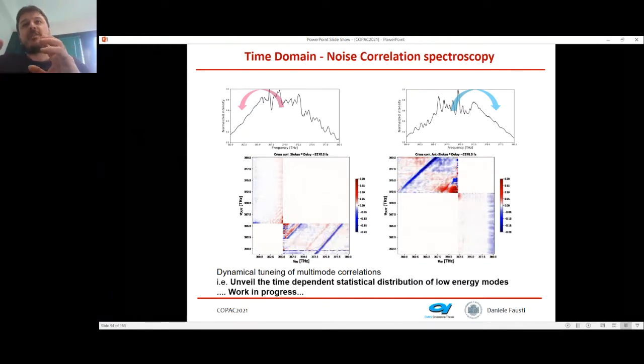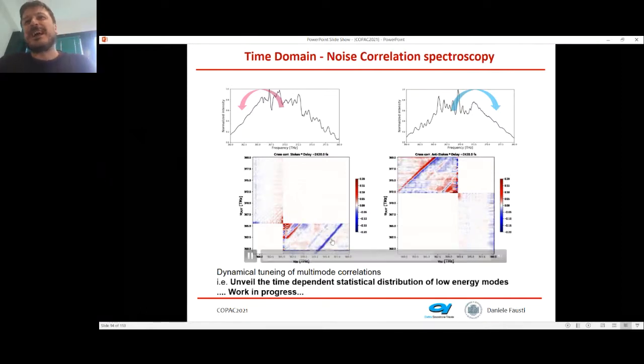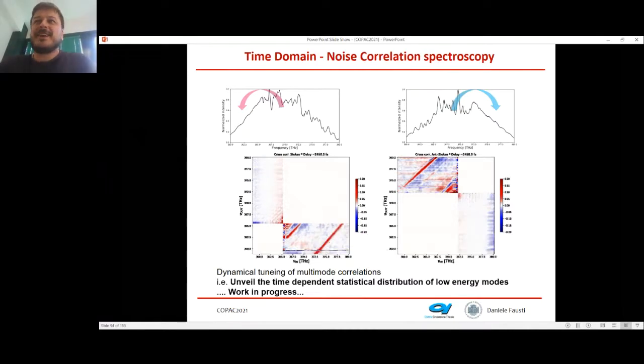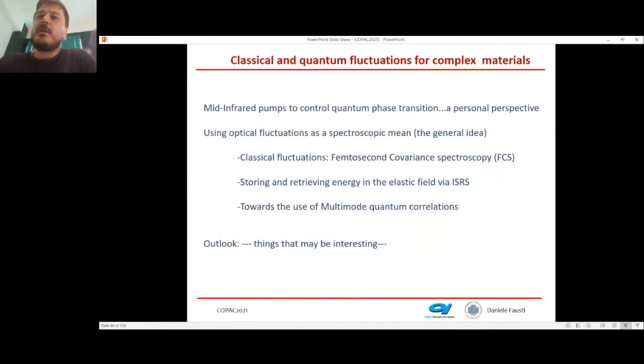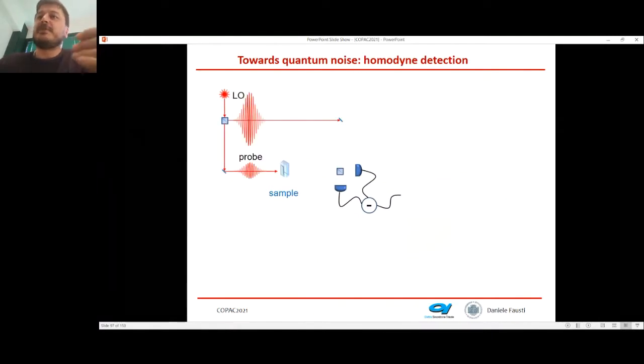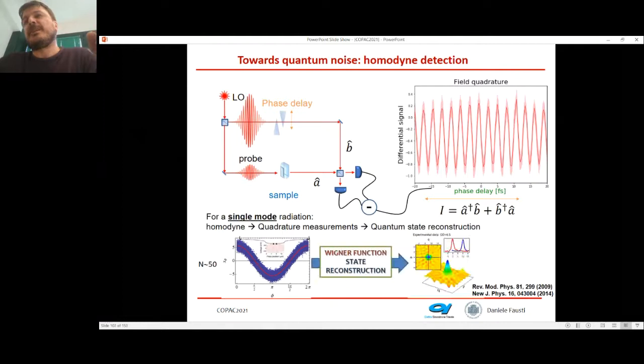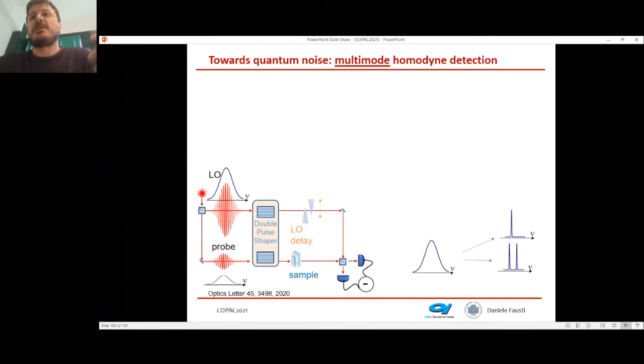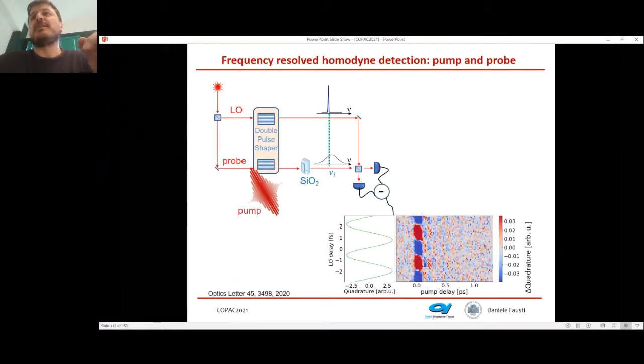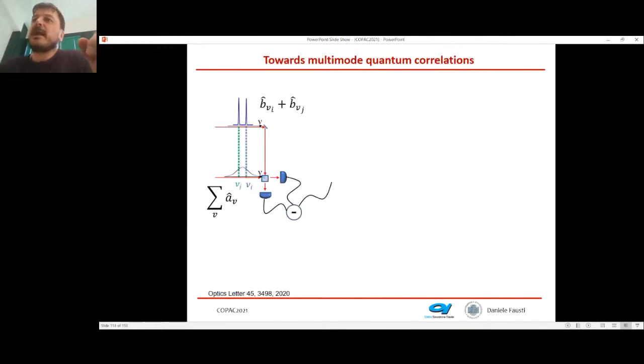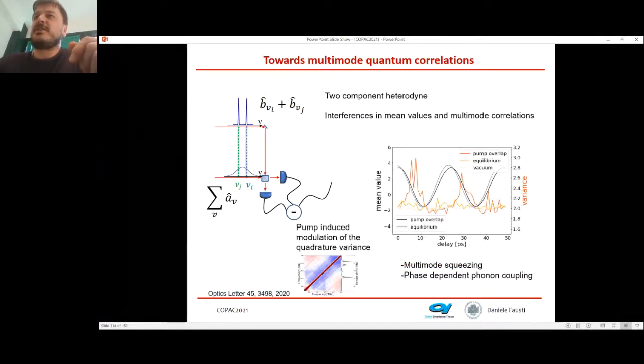So whenever the phonon mediates a scattering process which reduces the energy of the photon, it does so, but with the opposite sign, to increase the frequency of the photon. So the correlation reduces towards high frequency when it increases at low frequency, and vice versa. The idea is that we could use this to get a full statistical distribution of the phonon mode. And the last part of the seminar was to focus on how we push this towards using quantum fluctuations, and we have developed a technique for measuring multi-mode correlations with a few photons per pulse.